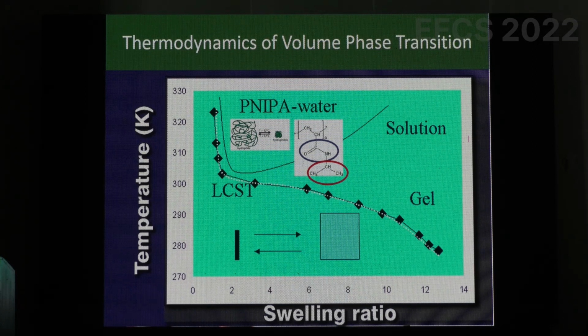At a molecular level, what happens is this polymer is swollen nicely at low temperature, and as you start increasing the temperature, it just expels all the water out and collapses, right? And that's the precipitation that happens.